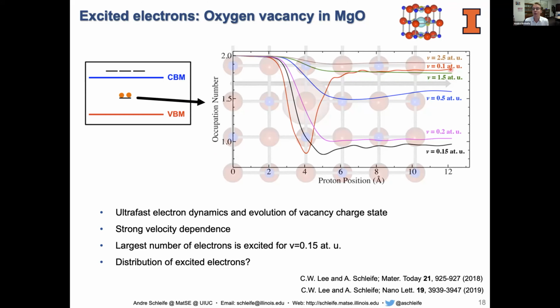And what we see is that this process depends very much on the velocity of the proton. Okay, slow protons, yeah, they do something at first, but then that effect essentially goes away again. And after the proton is gone, the vacancy is still occupied with 2 electrons. Same is true for fast protons. They move past the defect, but they don't change the occupation number much. However, there is a range of velocities, and this actually correlates with the energy distance of the excitation that happens in the material, at which you can very efficiently excite the defect state.